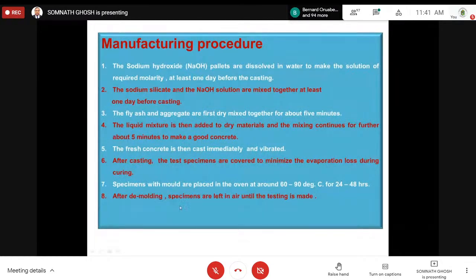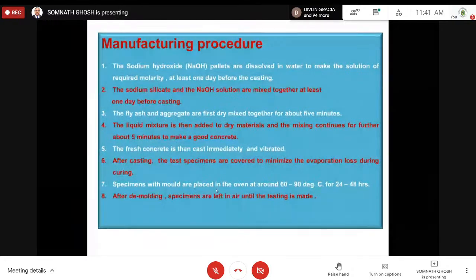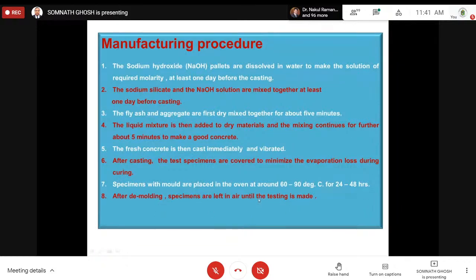And then finally, you will place it in the mold, and after a few hours, or maybe after 1 day, you can take the specimen from the mold, and depending on your requirement, you can put it in the oven at 60 to 90 degrees centigrade, maybe for 24 hours, maybe for 48 hours. All these things I'll tell you in detail. So this is the manufacturing, very simple, very simple.